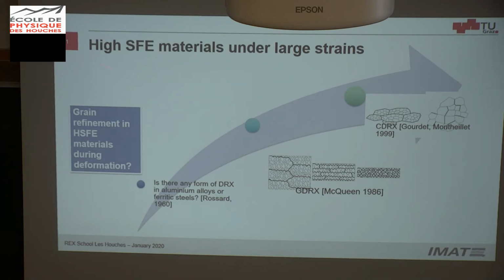Good. So the question of how to refine the grain in high stacking fault energy materials is not new. It was done, I have to calculate, 60 years ago, the first time, at least in the literature, by Rossard. He was asking, is there any form of dynamic recrystallization in aluminum alloys or ferritic steels? By the way, ferritic steels also are high stacking fault energy materials. So you can imagine the same of what I'm saying now, but for steels. Why am I not showing steels here? Because I basically don't work on steels, but you can imagine the same for ferritic steels.